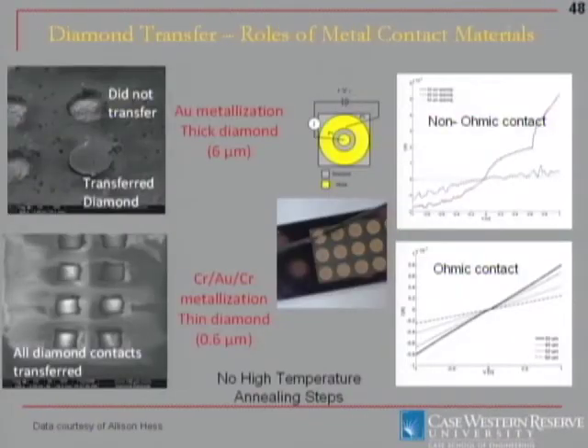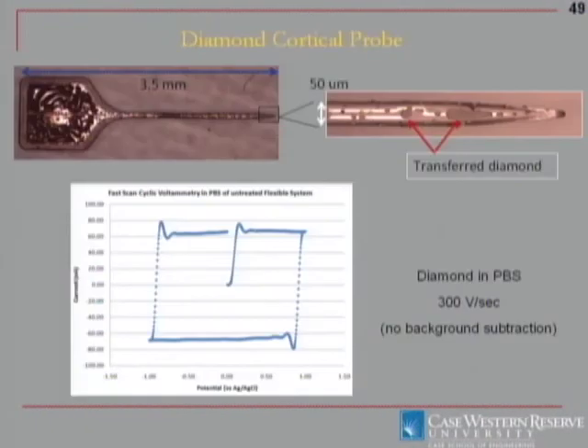Okay. We had to work on the contacts. I like showing pictures to show the difference between what a good electrode and a bad electrode look like. If the diamond popped out, this is what you would see. It's a good thing to notice that the contact is ohmic. This is especially exciting because once we put the diamond onto the polymer, we can't do any high temperature processing to anneal our contacts to get ohmic contact like you typically do. So in any case, we've got a working device.